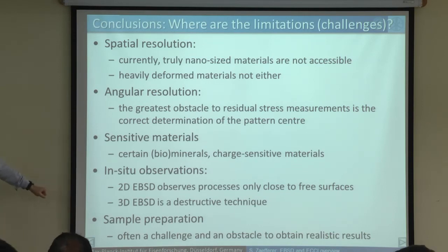But also in metals, you have multi-phase materials. One phase is soft, the other one is hard. One is quickly dissolving, the other one is not dissolving. Sample preparation can be the most challenging problem of making nice EBSD. And before you do a proper EBSD measurement, I always recommend stay a couple weeks in the lab, not weeks, months, and make a nice sample before that.